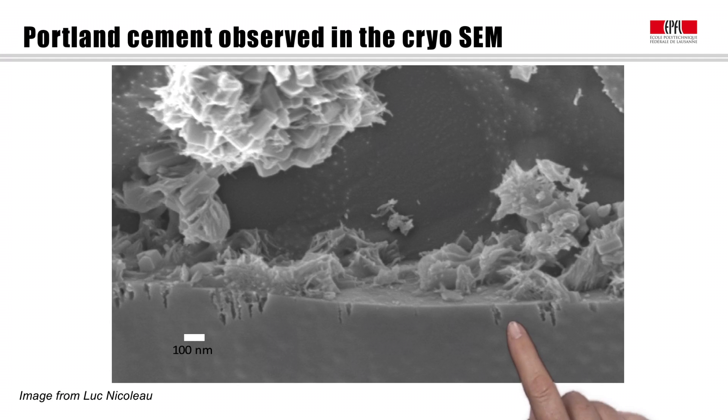And in fact, we can see these pits. We're going to come back to these pits. They're very important. And particularly on these pits, we can see there's no indication of any kind of covering. And this micrograph is at quite a high resolution. The bar here shows you about 100 nanometers scale. So even if there was a layer only a few nanometers thick, we would expect to see some indication of it. So really, this theory of the protective membrane that most people have been promulgating for a number of years now really just doesn't hold up to examination.